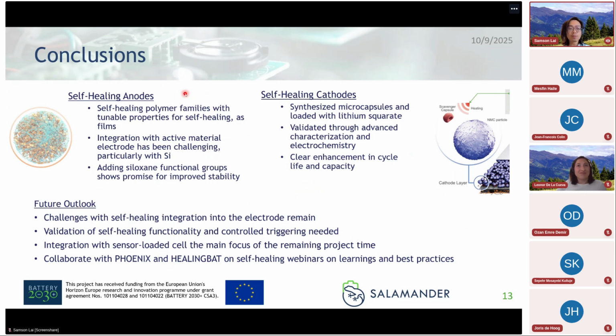We have developed them primarily as films, and integration with that has been challenging, but we've been able to iteratively design the polymers to make them more promising for the future. For the self-healing cathodes, we actually demonstrated this improvement enhancement, and that's been published, and it's quite a nice system, but it's still, let's say, not necessarily considered self-healing. It has an improvement, but to really get this smart functionality we would have to have something that you can trigger on demand and tune that with, for example, some sort of sensor.